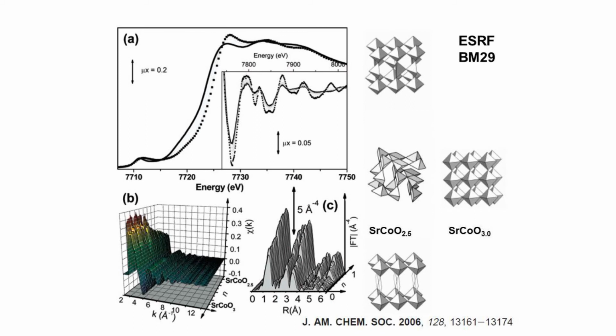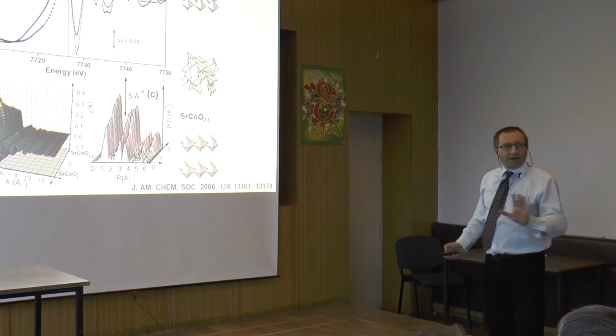Okay? The change of the XANES tells that we are changing the oxidation state of the transition metal as expected. Very interesting is also the EXAFS part. Let's look just at the Fourier transform here. We start from a brownmillerite phase, which is a quite disordered phase, because what is clear is that the octahedral layers are well defined, but the tetrahedral layer can be displaced in different ways, and different structural models are present. What do you see here? You see an impressive increase in the signal. And this is the first shell signal, and this is the less impressive increase.